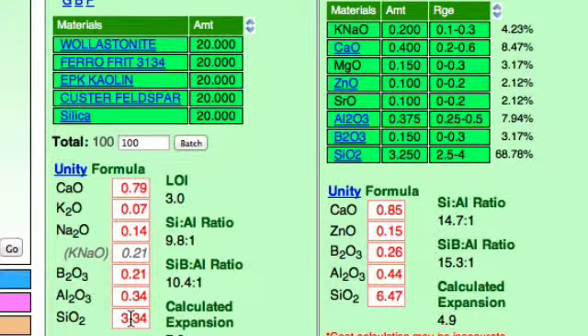Now let's compare this chemistry again. 3.3 of silica, all the others would be unchanged, and the average is 3.2. So I was able to put 20 parts of silica into this recipe that only totaled 80, and I've just brought the silica up to the average amount. And this is a glossy glaze, so I could put even more.